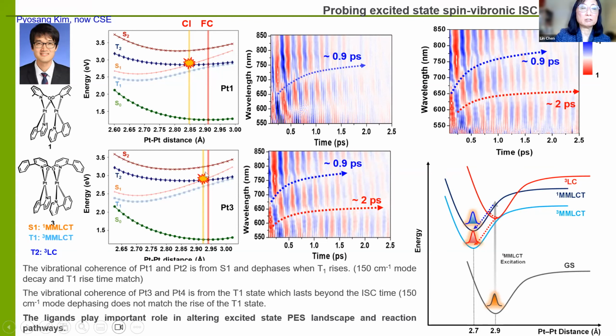and the rationale is that this Franck-Condon state, with the same geometry as the ground state, is close to a conical intersection of the triplet state. It undergoes really fast intersystem crossing, much faster than the period of the Pt-Pt stretching frequency. That's why the coherence is maintained. And there could also be two different parallel pathways. In this case, one is far away, so only one pathway is sustainable, but this one is close, so both pathways can be available.